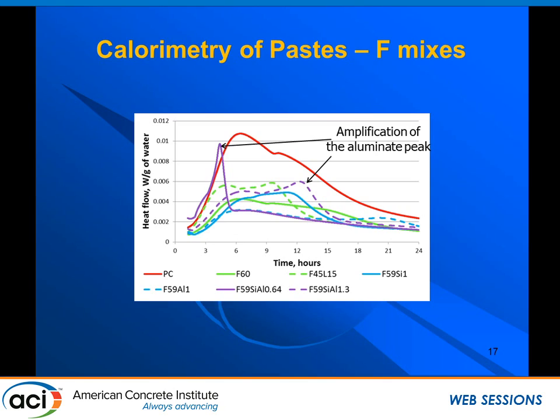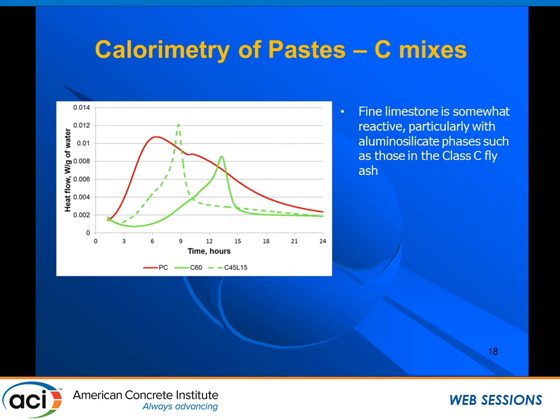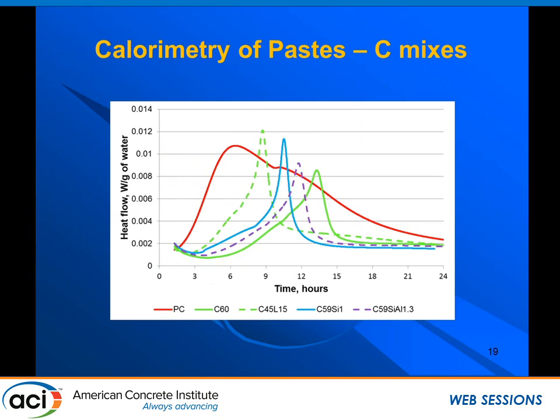And when we put in 1.3 silica to alumina ratio, again there's an amplification of the peak, but the shift to the left isn't really significant. For the fly ash, it's again the same thing—limestone really helps with the setting.